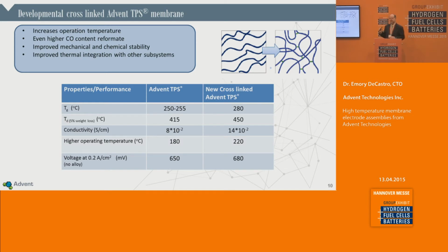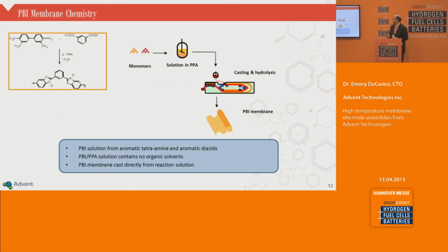Now, the nice thing about having a nice stable membrane matrix is you can cross-link this matrix and pull out even more stability from there. So, still considered a developmental product today, but we've been able to cross-link TPS. And now, as you can see, if you look at 5% weight loss, that happens now at 450 degrees C, so we've pushed it out from 415. Typically, we've shown this operating in our laboratories at 220 C, and because of that, you get a boost in the voltage and conductivity as well.